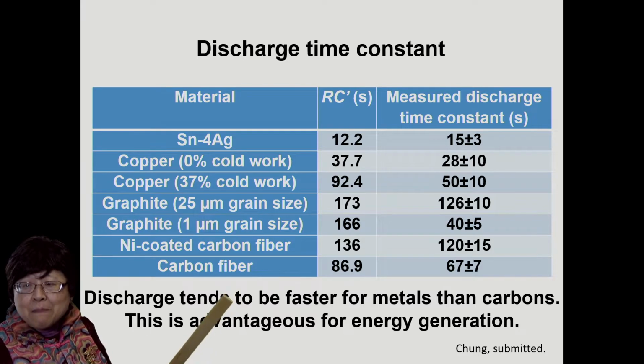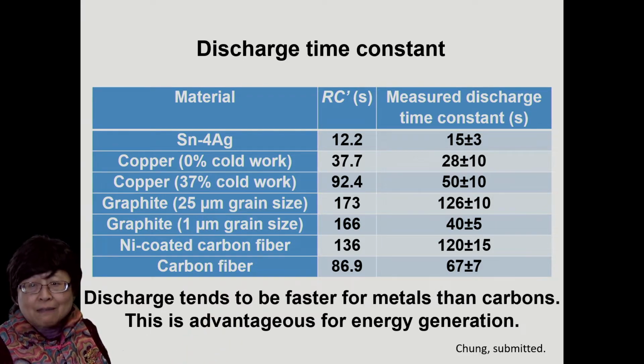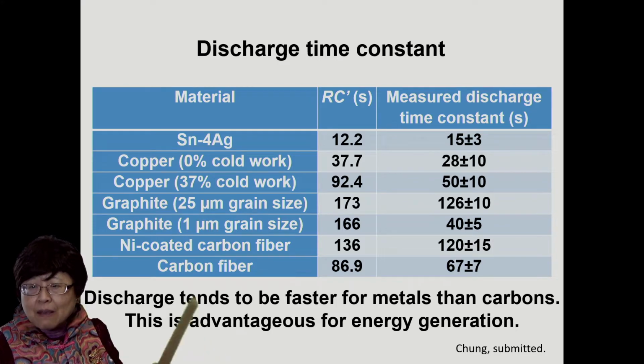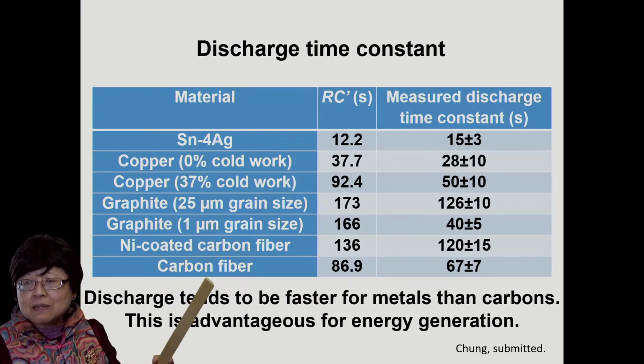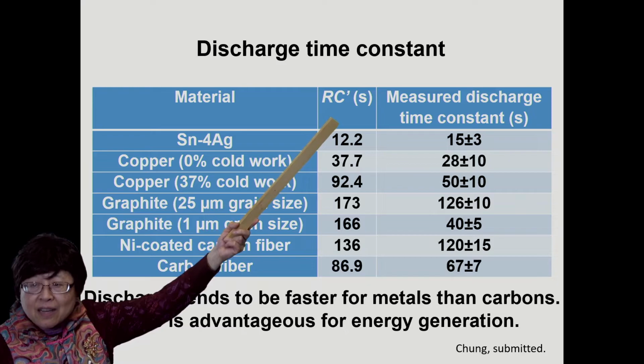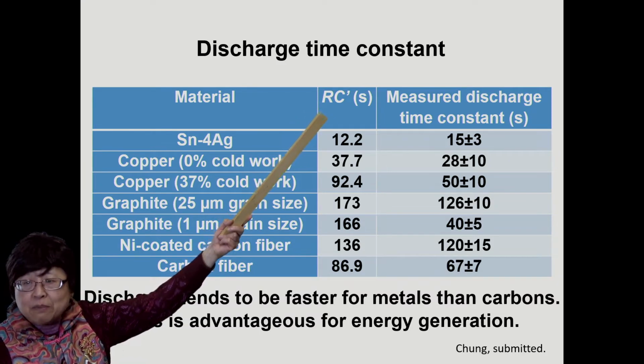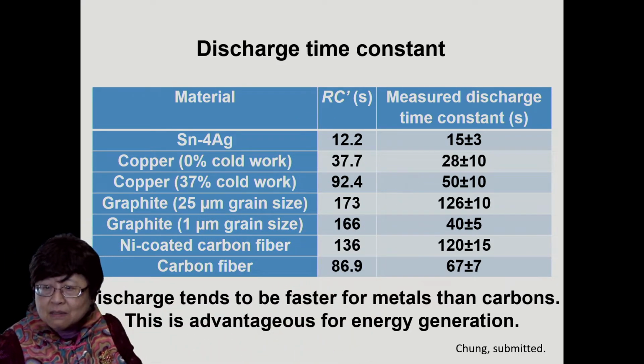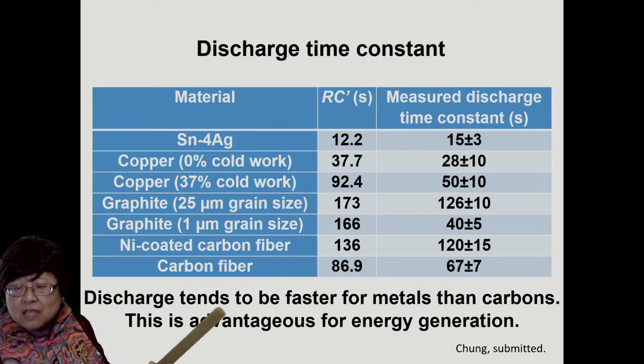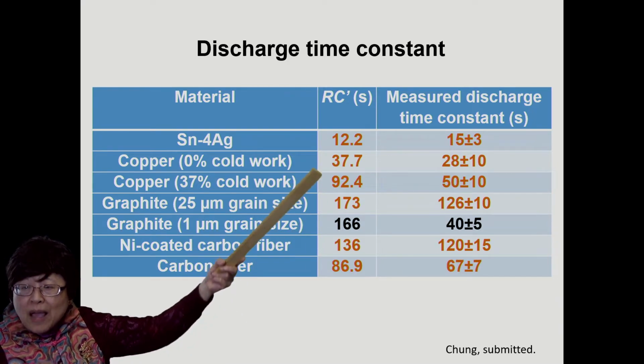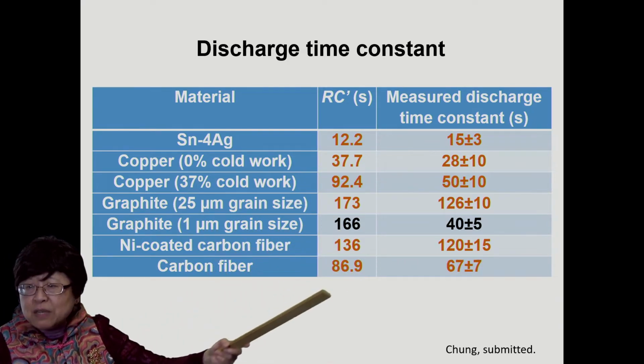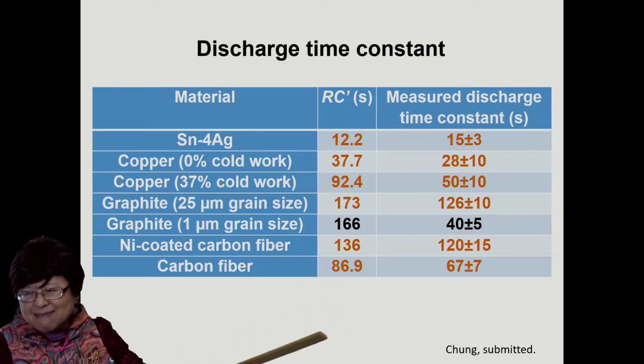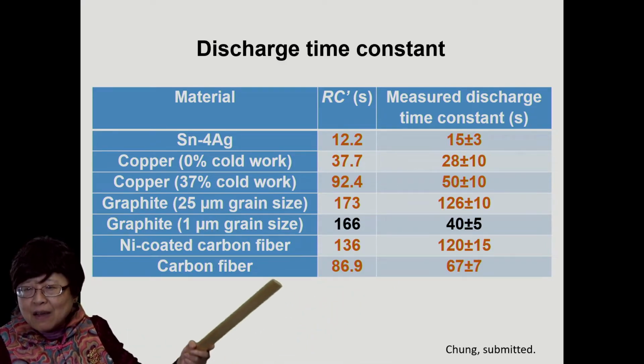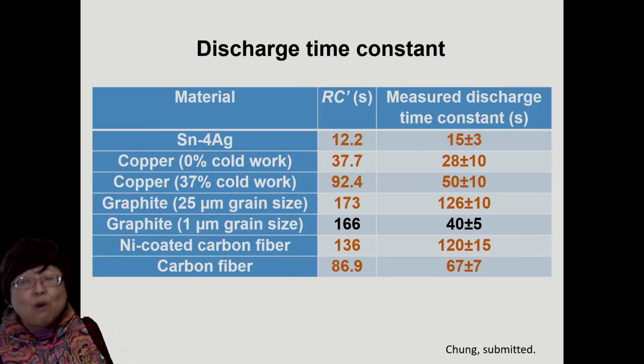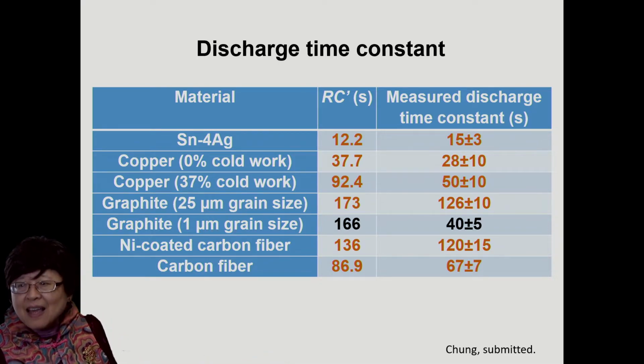Now, I mentioned that we have experimental support of that very simple model. And here it is. For a variety of metals and carbons, we calculate the discharge time constant, RC prime, and measure the discharge time constant. The discharge tends to be faster for metals than carbons. And for all the red rows, the agreement between the calculated and measured values is kind of okay. Not all of them are okay, though, but most of them are kind of okay.